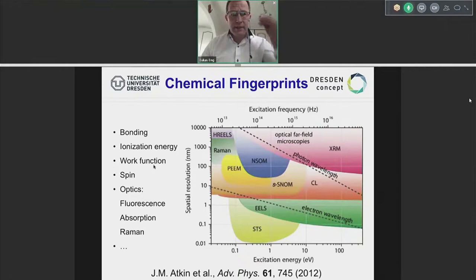Now, what kind of parameters could we really take as a signature for doing chemistry? For instance, looking at the bonds, you could actually measure quantitatively the bond strengths. This is something really common when you do imaging, because you're forming bonds with your tip and your sample, and you're breaking bonds. We could look at the ionization energies. This is also a very important feature. Ionization, actually the amount of energy that we have to impart on the system in order to separate an electron off the system, is equal to the work function. We could really look at the spin, which is also a character, as you know from Pauli, that is very important to understand. And then we have a set of optical possibilities where near-field optics goes in to measure fluorescence, absorption, Raman, and there's more that you could do.